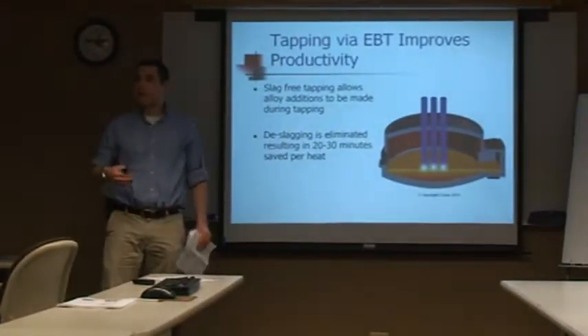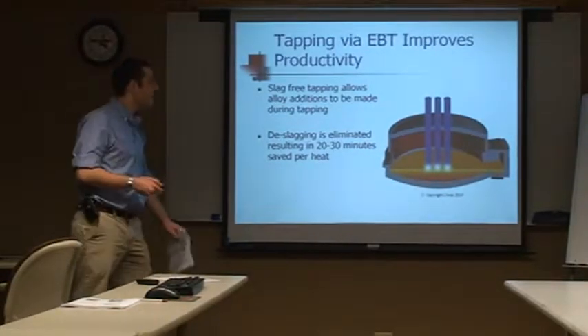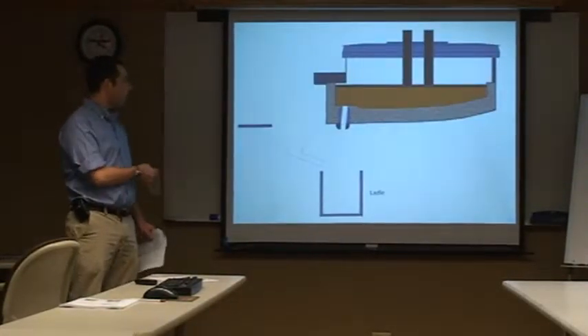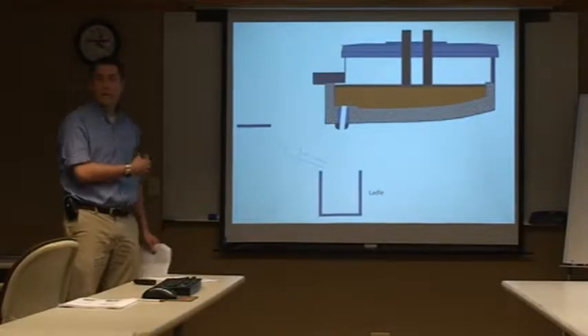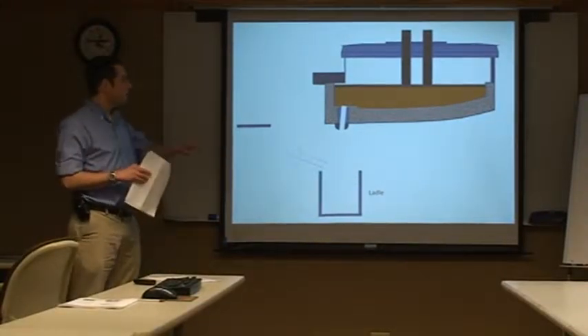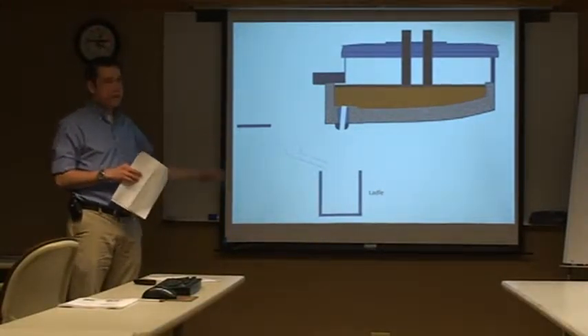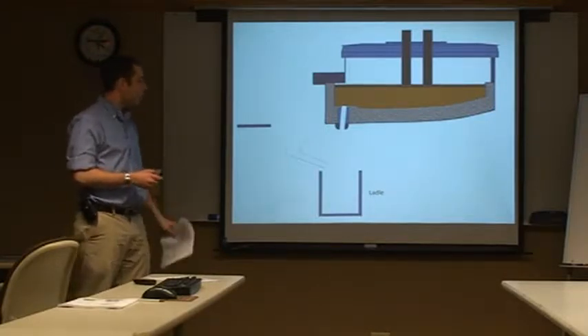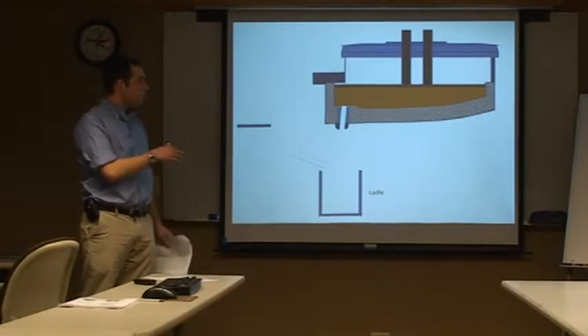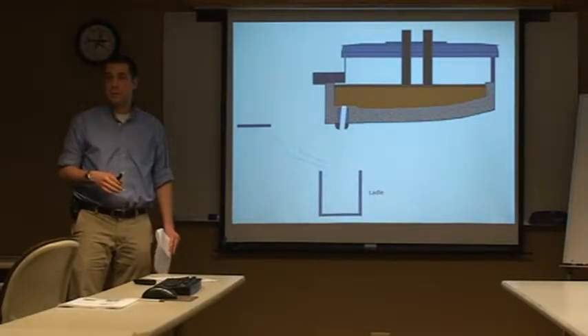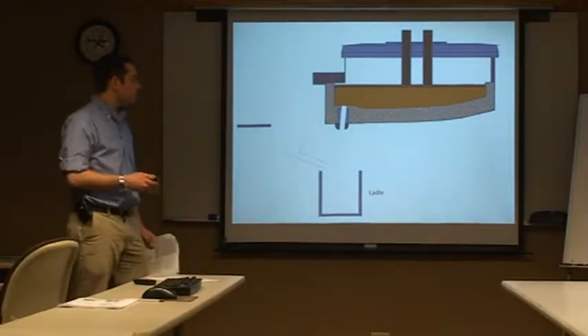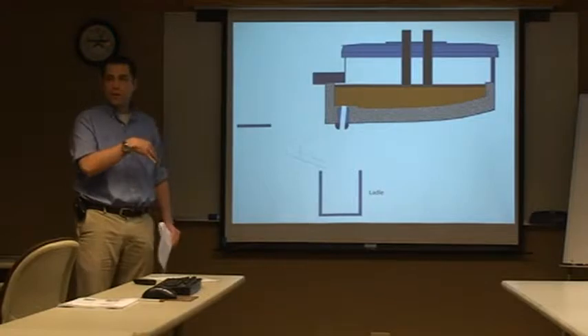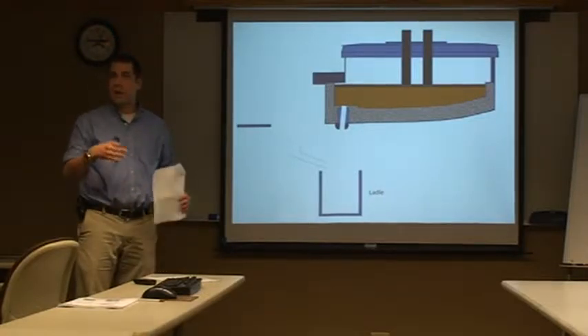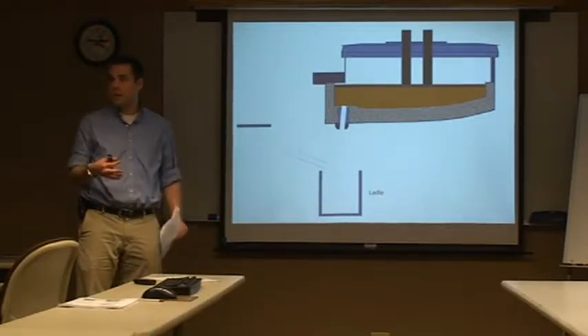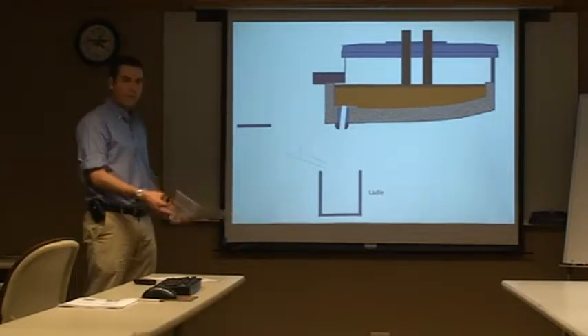We do utilize that liquid heel to kickstart the next heat that goes in there. And you'll see that in this slide here. This is an animation that's going to show you the tapping mechanism of the EBT furnace. You'll also notice that we take this opportunity to do some of our alloying, since when you're pouring the heat into the ladle, you have some inherent good mixing energy because steel's coming in a stream and filling up the ladle.